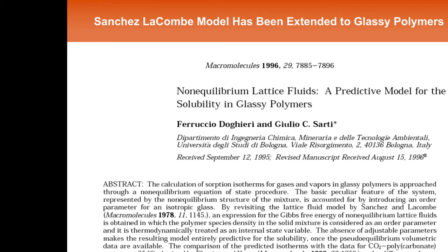You remember the Sanchez-Lacombe model, like the Flory-Huggins model, and the rest of them are statistical mechanics-based models, so-called lattice fluid models. The revised version of the Sanchez-Lacombe model to be applied to glassy polymers, Sarti and Doghieri called the NELF model, and that stands for non-equilibrium lattice fluid model. And so this is the NELF model description of those data. Now, what's important to note here is that unlike the empirical dual mode model, which has 3 parameters that have to be fit empirically to describe this data, there are no empirical adjustable parameters in this fit.